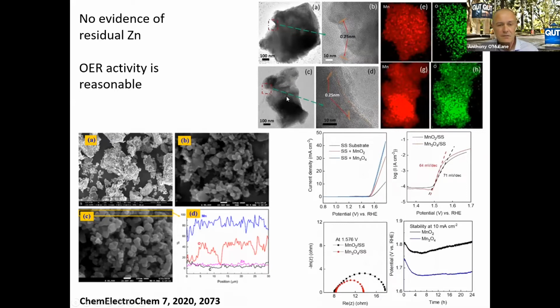If we look at some of the TEM images before and after we do that particular reaction, we can see here we have the phases due to the manganese 3O4 material. We can see that after oxygen evolution, the composition remains the same, but we're starting to generate some amorphous material at the surface of the crystalline particles we're using on our catalyst. So what we're thinking is happening is that the surface of the material is becoming amorphous, which is giving us our high activity, because there's a lot of evidence now in the literature that amorphous materials are more active than their crystalline counterparts.